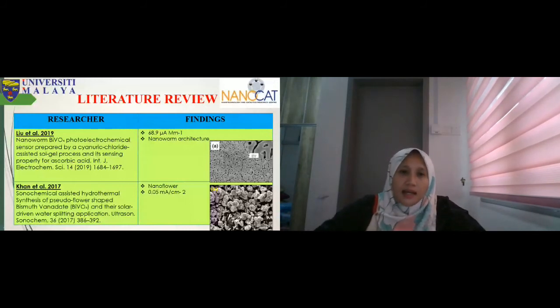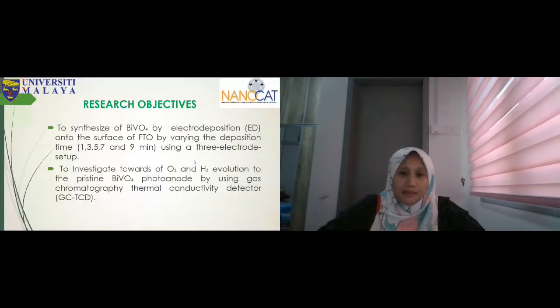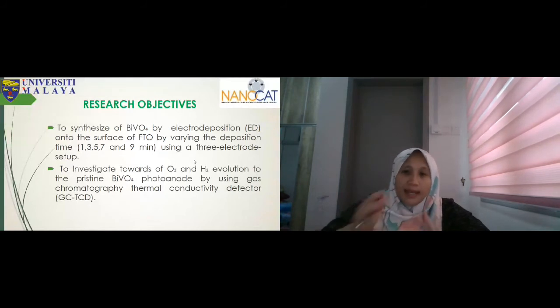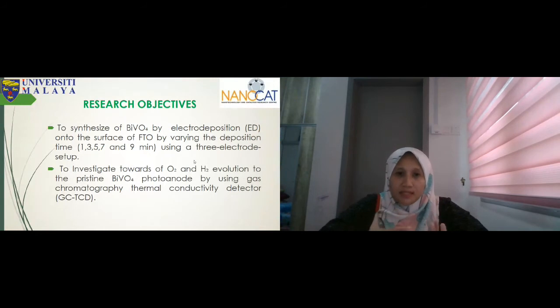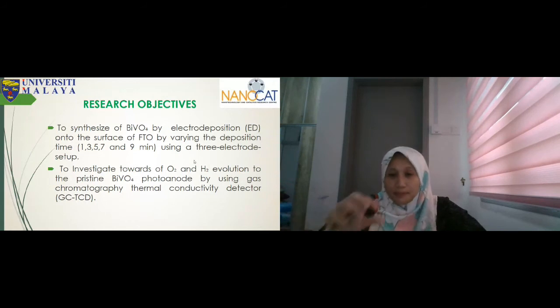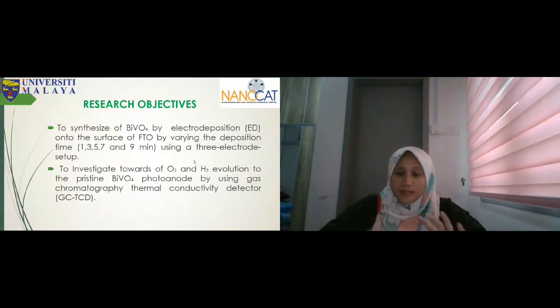In my case, I synthesized bismuth vanadate using an electrodeposition method, with FTO as the substrate, and I varied the deposition time: 1 minute, 3, 5, 7, and 9 minutes, using a three-electrode setup. Lastly, I want to investigate O2 and H2 evolution of the pristine BiVO4 photoanode by using GC-TCD, because right now, for water splitting, we need to prove that we can collect the hydrogen. We can see the bubbles at the platinum, and then we want to measure how much hydrogen we can get from our semiconductor. This is my experiment.